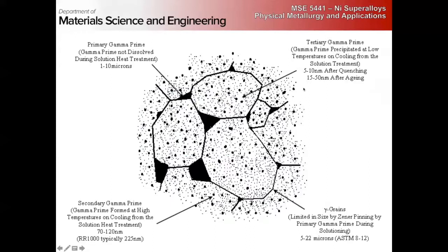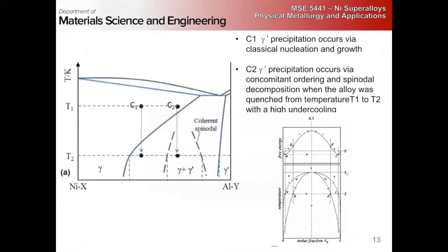So if you think about what's happening here, this very fine, nearly homogeneous distribution, right? These act kind of like GP zones, right? This gives us kind of a general lattice friction, a general strengthening, right? Then we have these larger, still very fine, 100 nanometer or so precipitates that are going to give us our main pinning obstacles for dislocation motion, right? So a very complicated system.